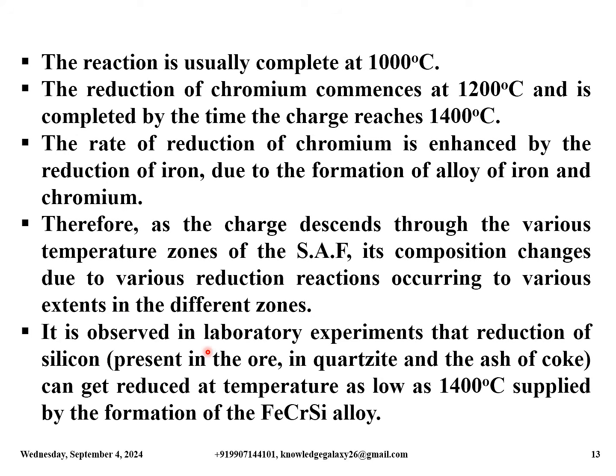It is observed in laboratory experiments that silicon present in the ore, in quartzite and in the ash of coke can get reduced at temperatures as low as 1400 degrees Celsius, aided by the formation of the ferrochrome silicon alloy.